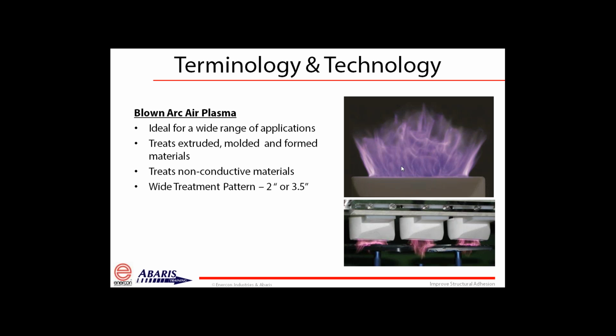One of the most important parts that you need to take into consideration for blown arc technologies is going to be the fact that it must be a non-conductive material. Given we're blowing an electrical arc across this, if you were to put a metal component or even a plastic molded component, potentially with metal inside it, and pass it through that arc, you would ultimately short that to that piece of metal. These applications typically range somewhere between 2 to 3.5 inches wide, depending on your application specifically. So it does allow you to treat a fairly sizable portion on many parts that are created.